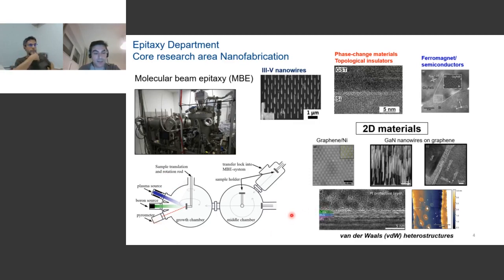And in addition to that, you usually have some other chambers that are used first to load your sample inside the system, and in between the so-called load lock chamber, you usually have a middle chamber that, of course, prevents your growth chamber from being vented every time that you load the sample. So ideally, your growth chamber always stays in vacuum.